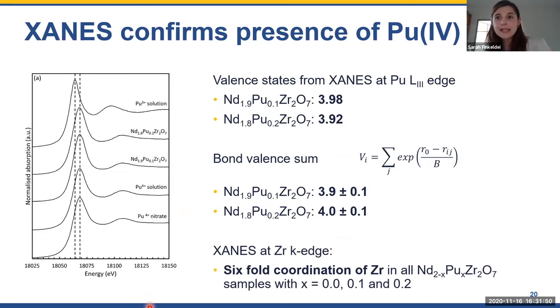To have a basically complete analysis of the system, we also performed XANES spectra at the zirconium K-edge, and we obtained 6-fold coordination of zirconium in all of the samples, which was not surprising at all, since the B site is 6-fold coordinated in a pyrochlore.